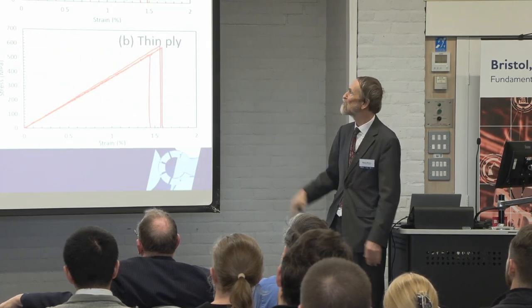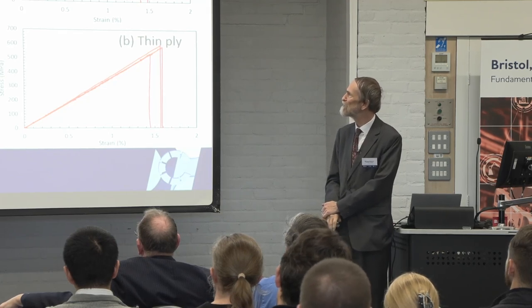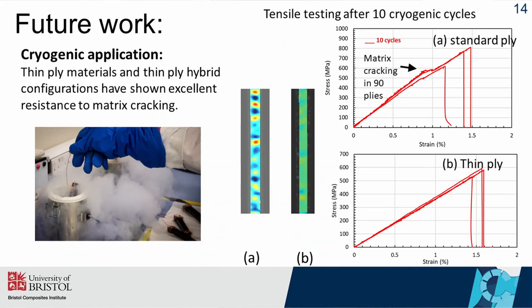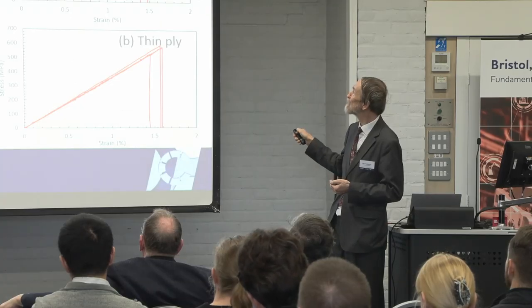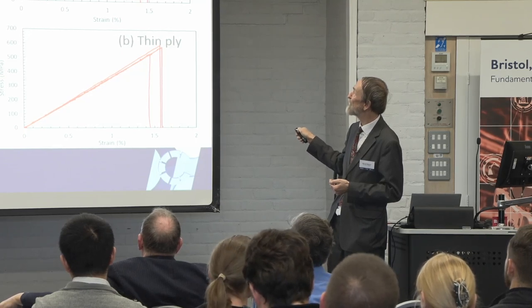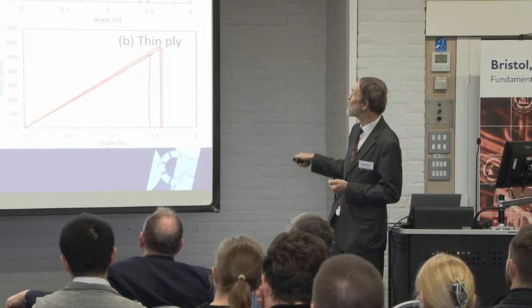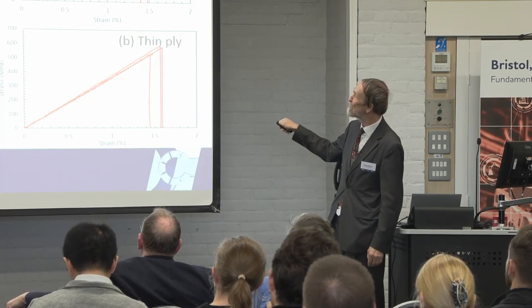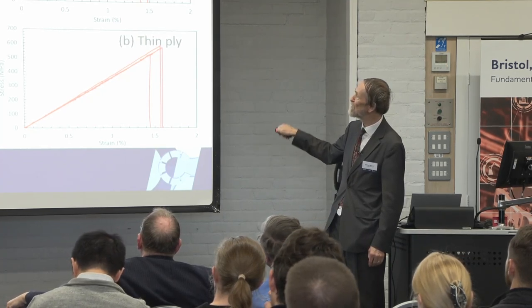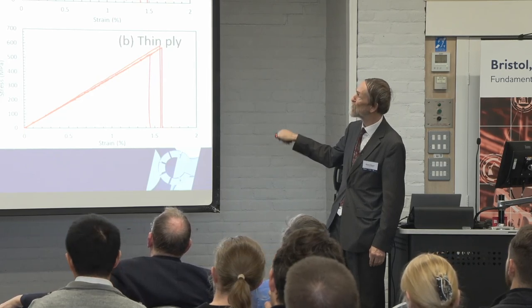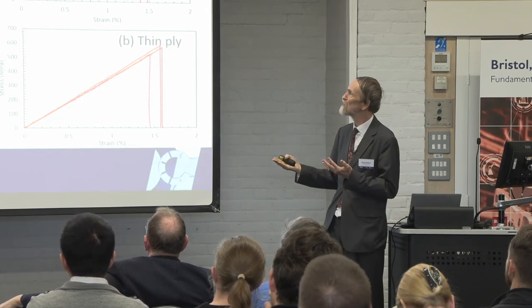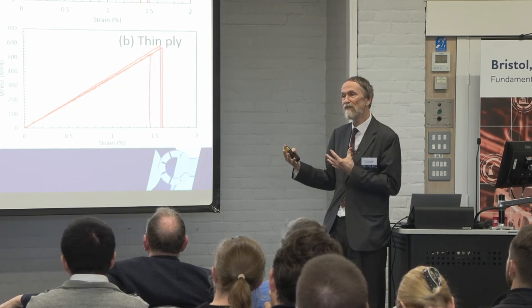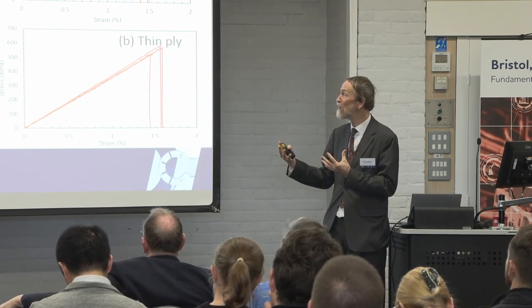And potential future work is looking at cryogenic applications of thin ply materials. So this just shows a few results from a standard thickness material which has been dunked at cryogenic temperature and then been loaded in tension. And we see that with the standard ply thickness, we get this matrix cracking and non-linearity, whereas with the thin plies, it's linear to failure. And no transverse cracks are visible here on the edge of the specimen, the DIC, compared to all these transverse cracks you see with a thick ply.